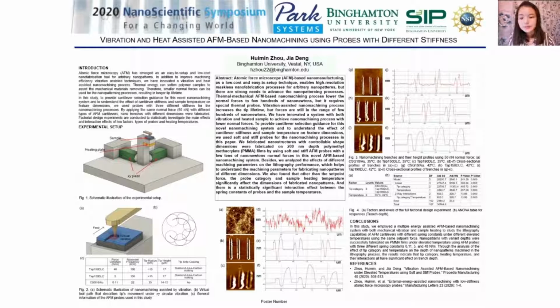And therefore, we get to the conclusion that other than the setpoint force, the probe category and sample heating temperature significantly affect the dimensions of fabricated nanopatterns, and there is a statistically significant interaction effect between the spring constant of probes and the sample temperatures.